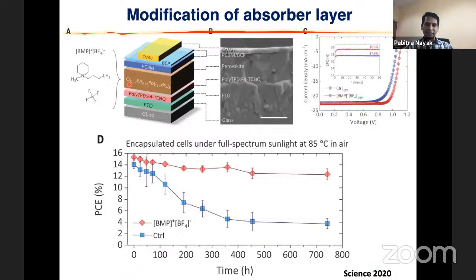What we showed is this formulation, which has now gone really complex. As I said, the ABX3, I can take different compositions. So here we have taken different compositions of the lead, the organic cation, and the halides. And to that I've also added an additive, a very small amount. These small things do very good chemistry to this material and make it very stable. You see that without those materials, the stability goes really down over time, but with this, it has improved. And if you just encapsulate, and we have further studies, we can get like 3000 hours of stable perovskites in encapsulated state. So we are getting close to there, we are not there.